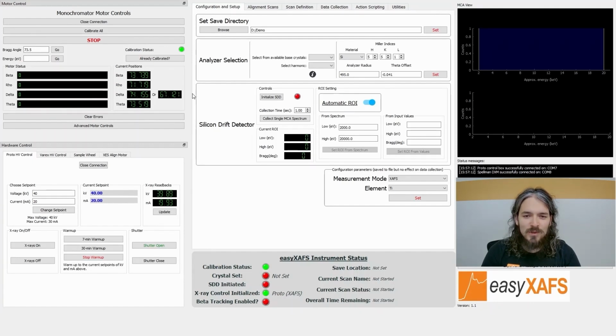The motor controls for controlling the position of the components are at the top left. At first power on, the motors take a couple minutes to calibrate. Here the calibration has been completed already. Control of the X-ray tube is at the bottom left. Here we can change the X-ray power setting and open and close the shutter. When you first power up, you have to warm up the X-ray tube, but for the demo, we already have the X-rays warmed up to 40 kilovolts and 20 milliamps. Now we'll continue to the configuration and setup in the middle.